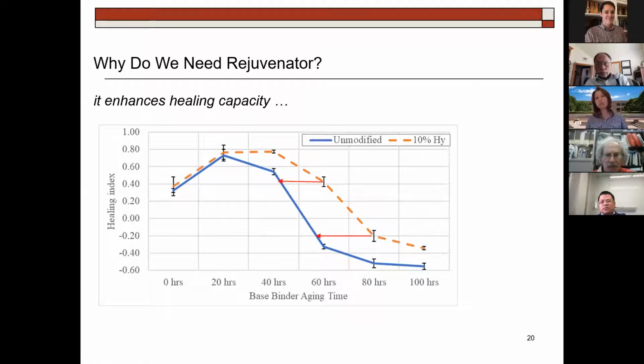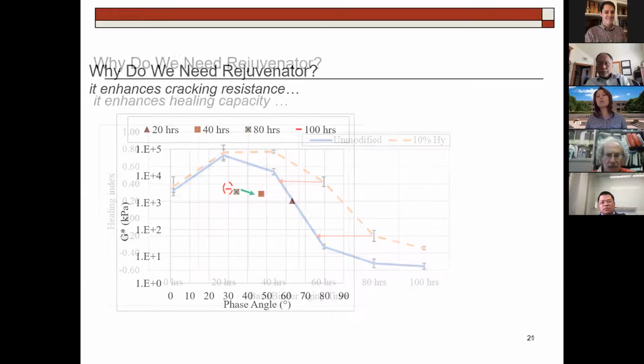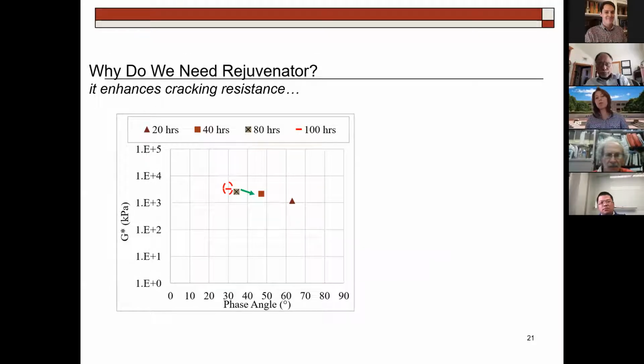And here is the rejuvenator proof of it. We added this rejuvenator, very effective. You can see in some scenarios, it does a pretty good job. But as it gets to this end of healing, I can't bounce it back. It's just too late. The healing is too low, it won't be restored. Maybe it improved a bit, but it's not enough to reduce cracking. I proved that with the Glover-Rowe parameter.